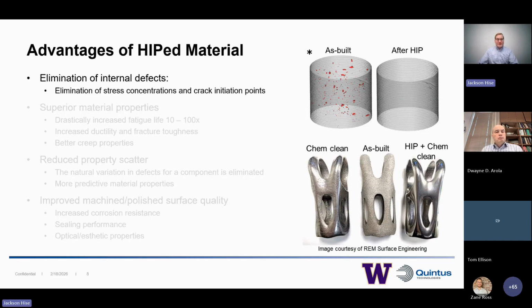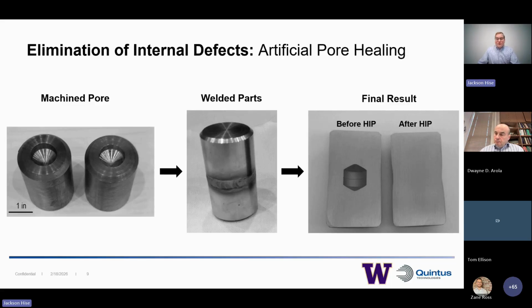So if we want to take a step back and just look at some broad overall advantages of HIP material, first and foremost, HIPping the material eliminates internal defects. This elimination of stress concentration and crack initiation points leads to superior mechanical properties. If we want to take an extreme example, we can see this machined artificial pore here. Here we machined a 1-inch diameter pore into the component, then welded these two parts together. After we HIP, we see that we fully resolved and healed this hole or this pore within the material.